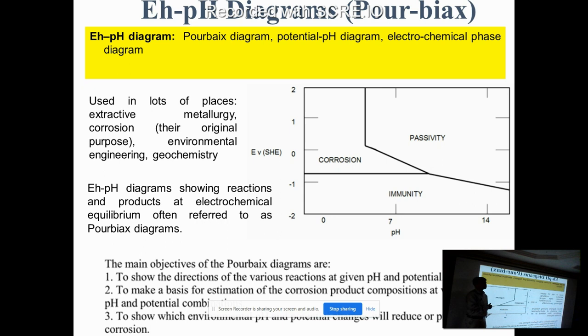See, acidic pHs definitely undergo corrosion because, you know, in acidic environments H plus ions are more often there. So what will happen if H plus ions are there? H plus ions are good oxidizing agents. They try to pull the electrons. So definitely corrosion will be more. So what I do, instead of H plus being more, I keep H plus ions low, at higher pHs. So I will fall in alkaline zones. In alkaline zones, I will fall in the passivity zone, or I will be in the immunity zone if my potentials are negative. So there is no corrosion at all.